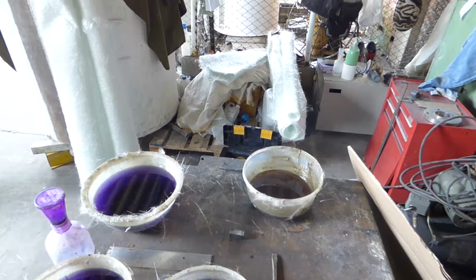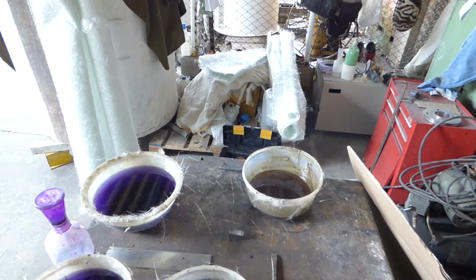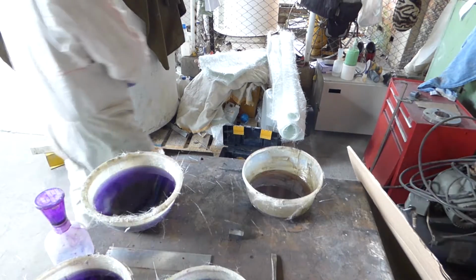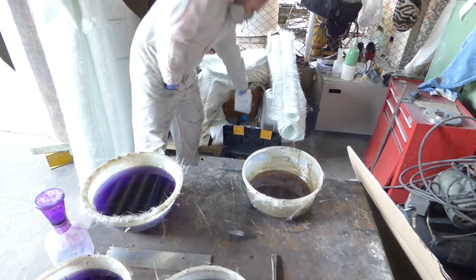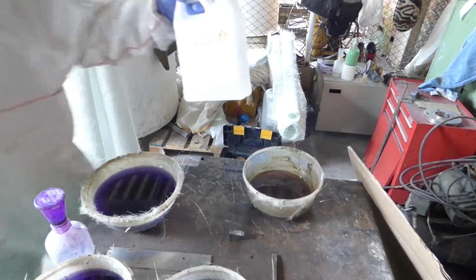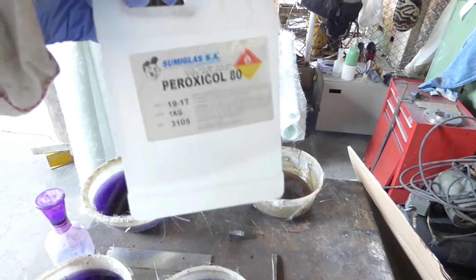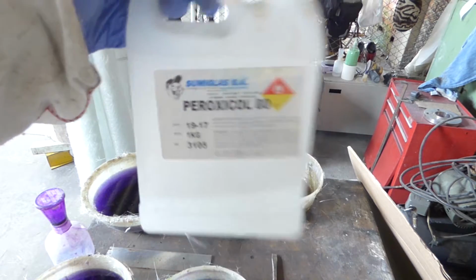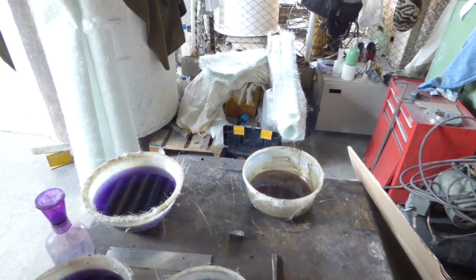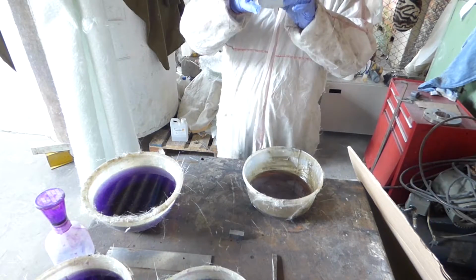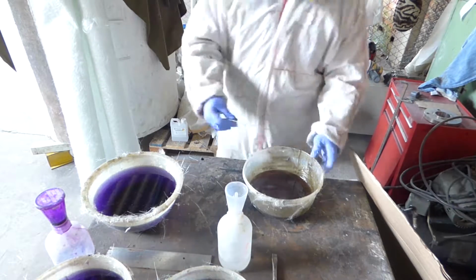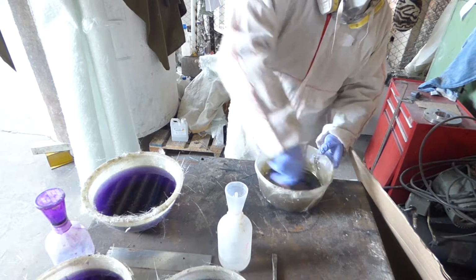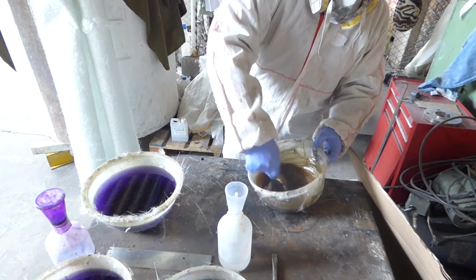Now the catalyst. In this case, we are gonna use 0.5% by volume. So if I'm weighing 1 kilogram, I'm gonna use 5 milliliters of catalyst. This is going to give me about 20 minutes to work with before the gel time.